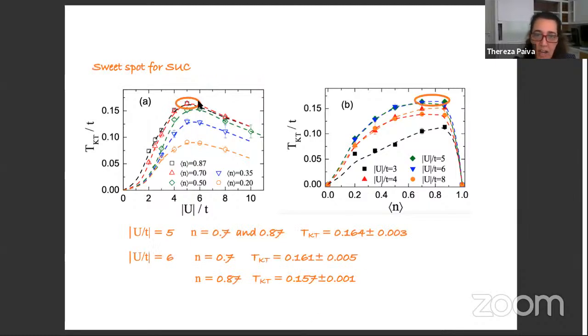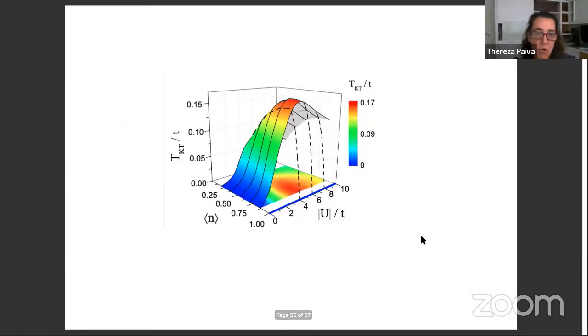And also, if we look here and here, this is the actual maximum for the transition, and we see that for U equals 5, either having 0.7 or 0.87 density leads to the same result, because in this plot here it's easier to see they are flat. And this is the maximum Kosterlitz-Thouless transition we obtained. I forgot to divide here by t, but this is in units of hopping. And here for U equals 6, which is right beside here, we have a similar result, but this is where the temperature is higher. So this is just a 3D plot with all these results. And with this, the red region here is the sweet spot for the Kosterlitz-Thouless transition, and where experiments should focus when doing experiments on the attractive Hubbard model.